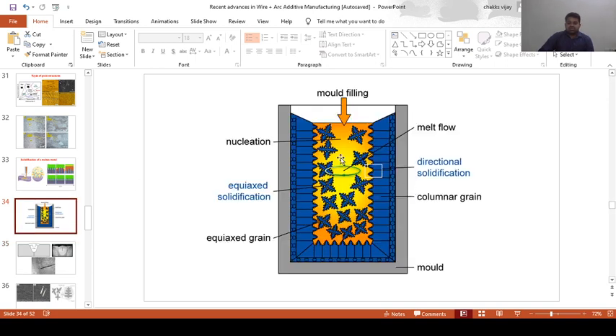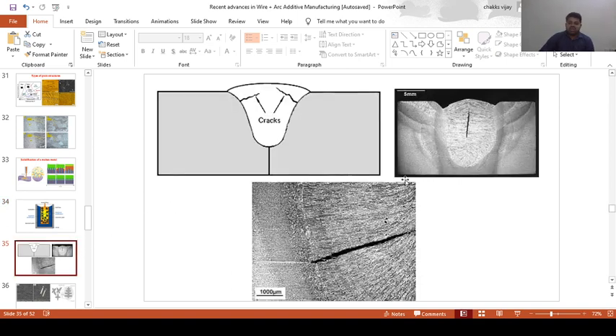Whenever you have sufficient interdendritic liquid in this mushy zone, where some semi-solid liquid will be there, that particular liquid is called interdendritic liquid. If that interdendritic liquid is sufficient, then it will heal all these cracks and voids, wherever these cracks happen, it will go and heal.